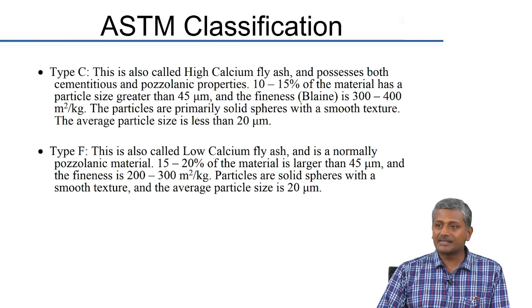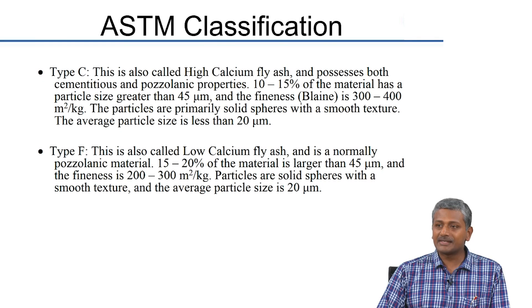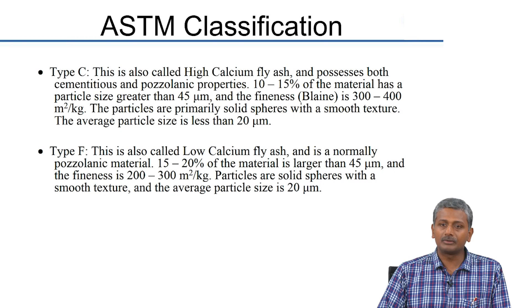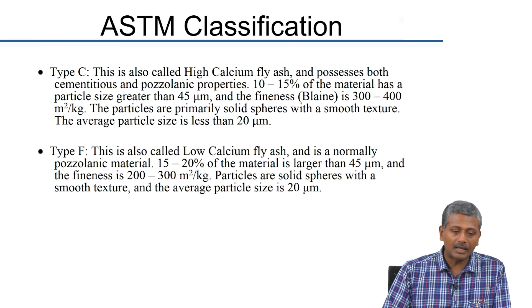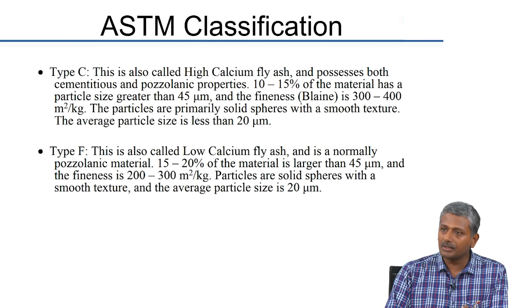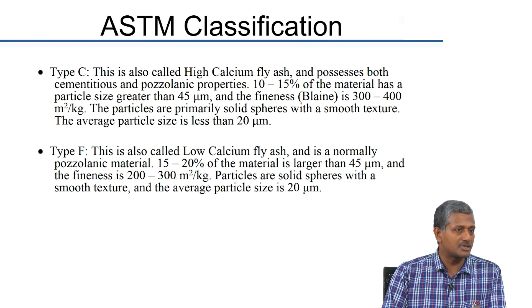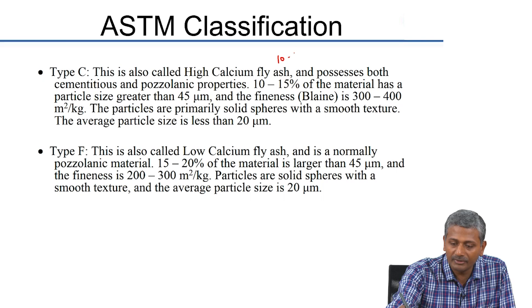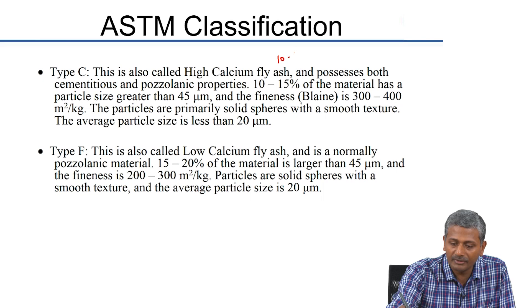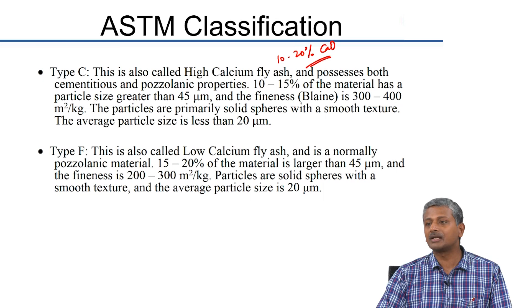As per ASTM — the American Society for Testing and Materials — fly ash is classified as type C or type F. In India, we classify fly ash in terms of high calcium or low calcium, which essentially means the same. Type C is high calcium fly ash with generally around 10 to 20% calcium oxide, and because of that significantly high proportion of CaO, it possesses both cementitious and pozzolanic characteristics.